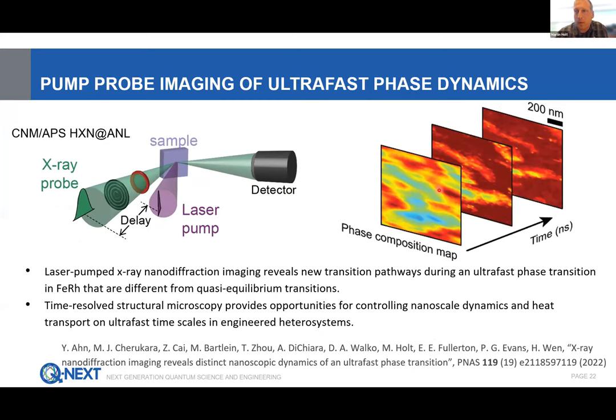Okay, acoustic dynamics. So I'd like to talk to you also a bit because people were talking about heat transport on the pump probe experiment that was recently done, driven by Haidan and Yunshun. And this is looking at a phase transition going across a photo-excited phase transition within the context of this unique local volume. So we can microstructurally map this 1 micron little square at a 20 nanometer level. And then understand the transition that's being bound by the frozen heterogeneity, the microstructure and the mosaicity within that unique little real space imprint and how the heat transport then re-equilibrates within it. And I think that gets to some of the questions of metastability and overall response to frozen disorder that some of the other speakers were talking to too.